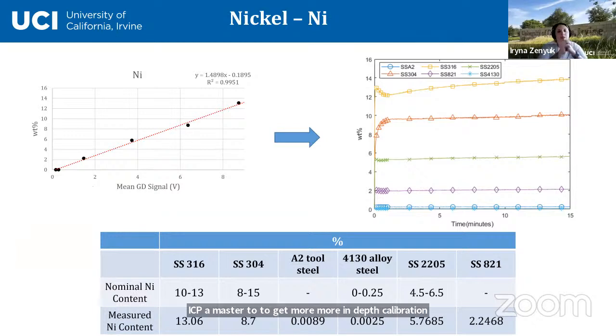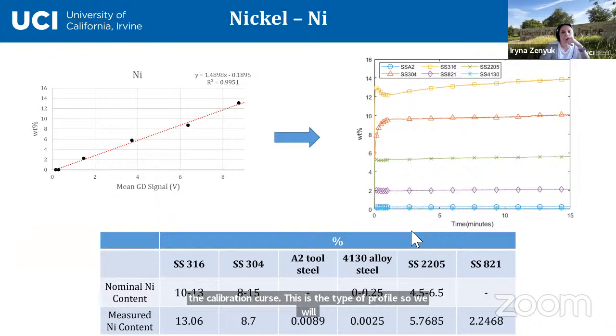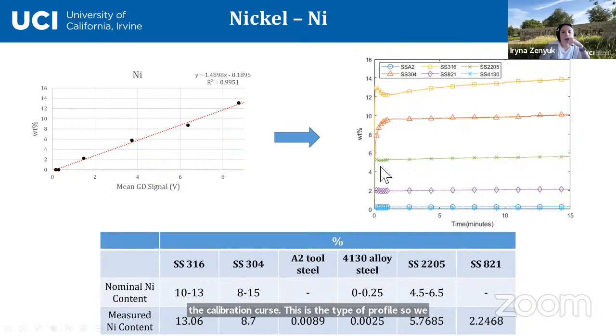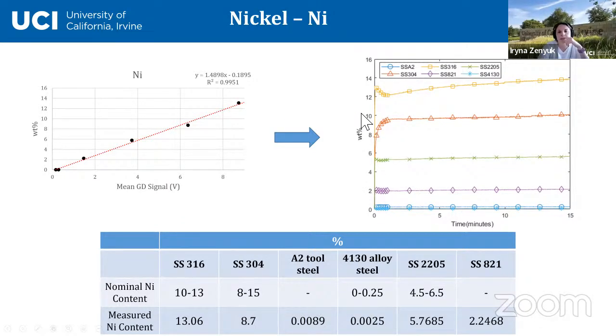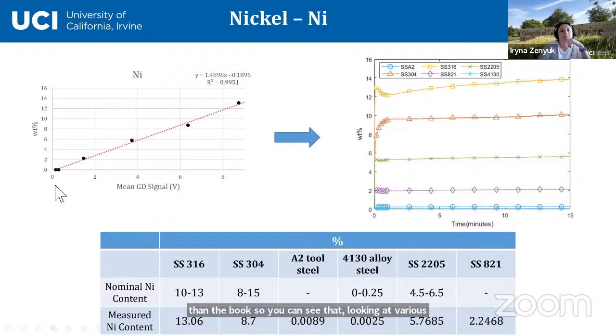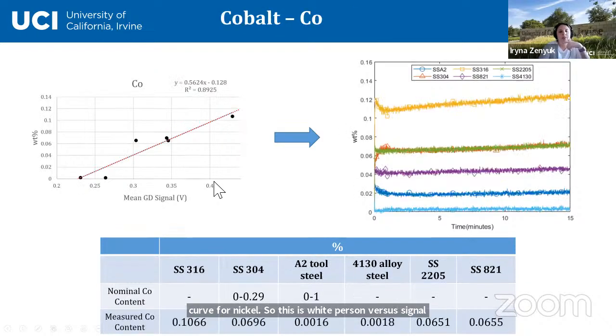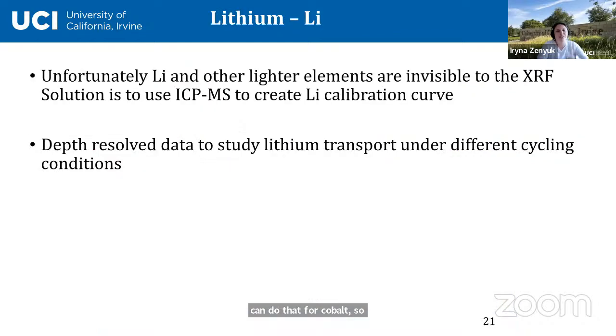So if you look at the calibration curves, this is the type of profile we would get from the glow discharge instrument. You see at the interface, there is some interfacial phenomena happening here, so the composition of the surface is different than the bulk. Looking at various stainless steels, we can create a really nice calibration curve for nickel. This is weight percent versus signal of glow discharge in volts for nickel, and we also can do that for cobalt. So it's a neat way to calibrate the instrument.